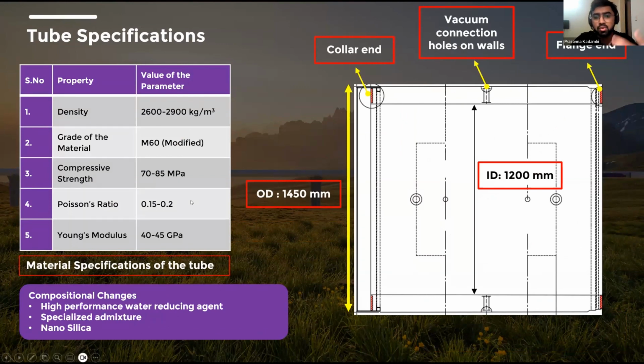If I talk more about the material, what exactly is the specification of the tube? We can observe that the current composition that we are utilizing has a density that can vary from 2600 to 2900 kg per meter cube, depending upon a slight change in the admixtures of the entire composition, in terms of the sand, the cement that is being added, and the aggregate as well. As for the grade of the material, we started from a readily available M60 material and modified it in order to gain these compressive strength parameters, and also to arrive at an optimized solution wherein it has better strength in terms of its tensile capabilities as well as the compressive loads which are inherently acting because of the vacuum load on the tube.